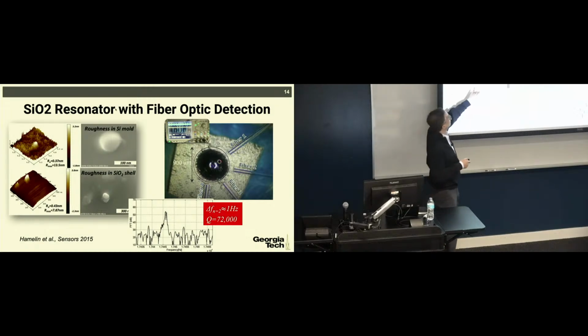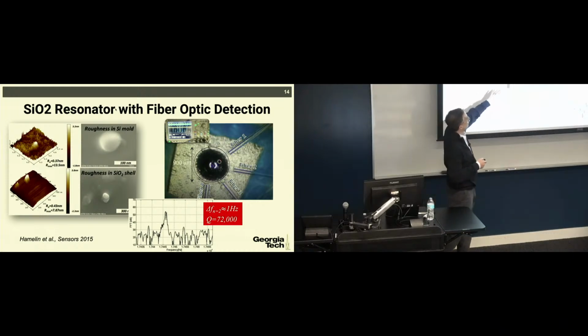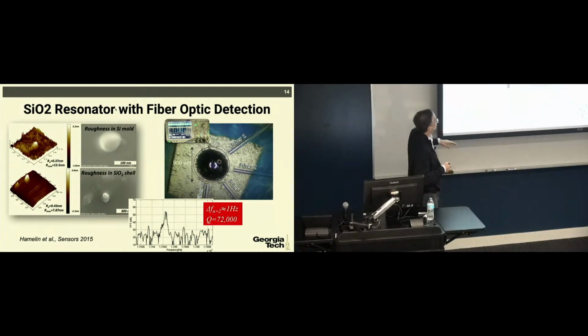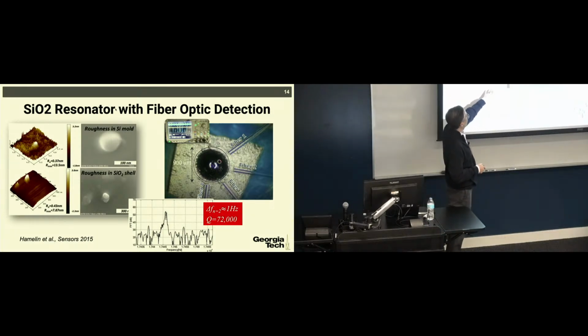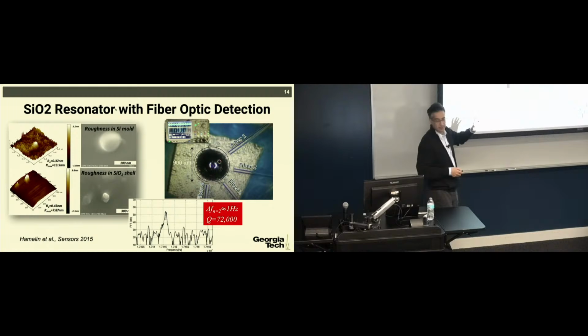So we did a lot of AFM-type surface measurements, and we saw that actually the roughness was pretty good in these thermally grown oxide films. They were all on the order of a few angstrom, but maximum roughness can go up to about 10 nanometer or so.